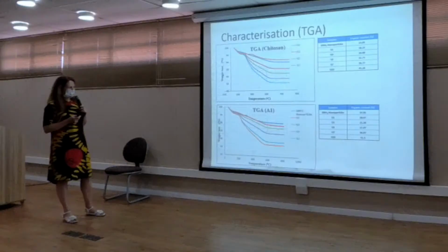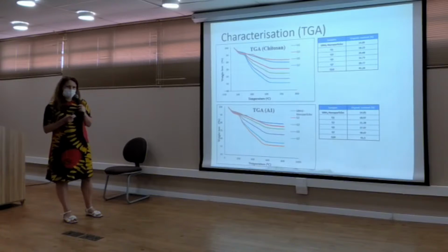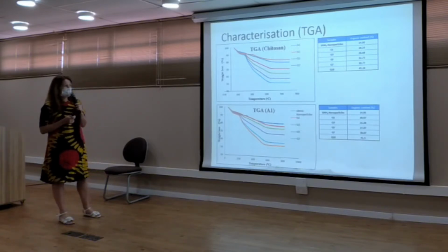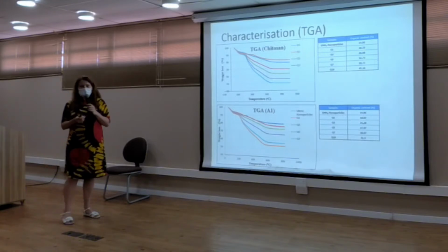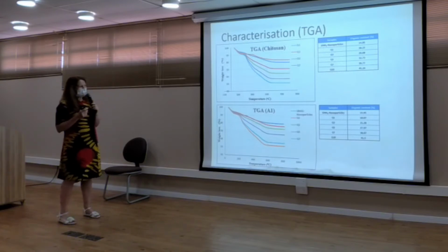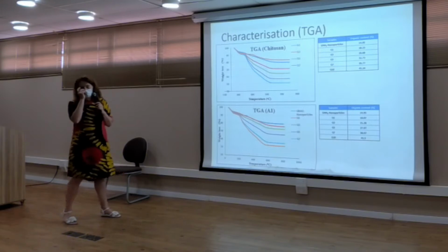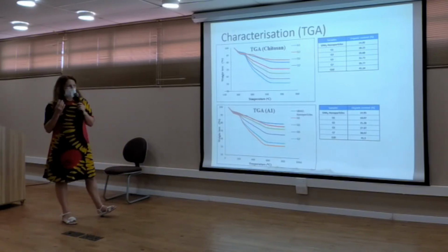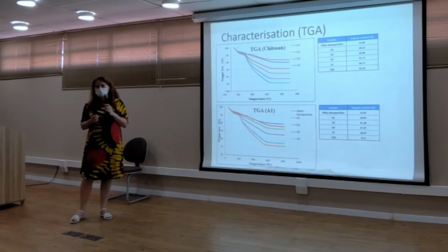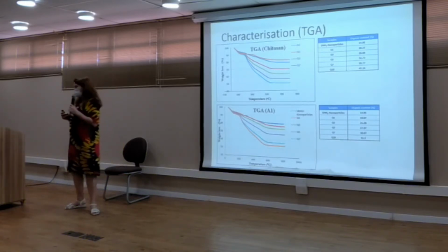So we did characterization of these nanoparticles as well. We looked at the organic and inorganic matter using thermogravimetric analysis, just to make sure how much organics we have increased at each time when we put an extra layer on the sample. We didn't do it after each layer because it's very time consuming and expensive. So we just did it for amino-functionalized silica nanoparticles, and when we put one quadruple layer, it means 4 layers. Q1 is 4 layers. We measure the organic content, and after this we put another 4 layers, and we measure the organic content, etc., until we reach Q10, which is 40 layers, and we measure the organic content.